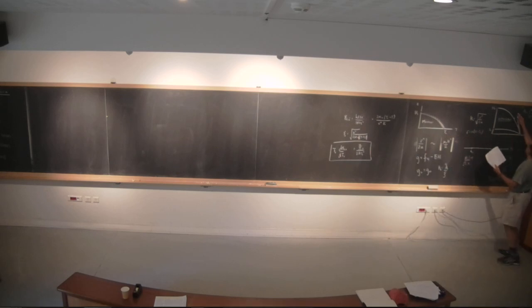That's a very useful result, because even though you may not be able to go to the extrapolation of this to zero temperature, you can get an estimate of the correlation length. This is xi naught squared. Remember, xi naught squared is h bar squared over 2m a Tc.